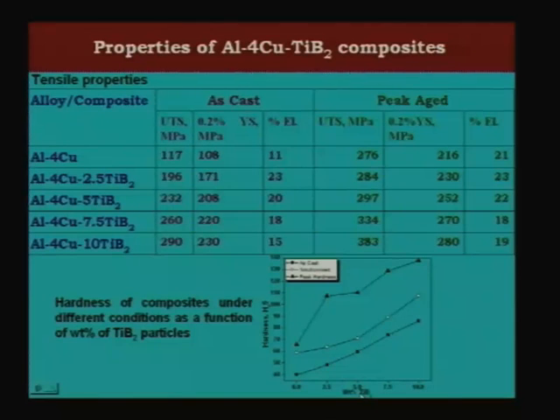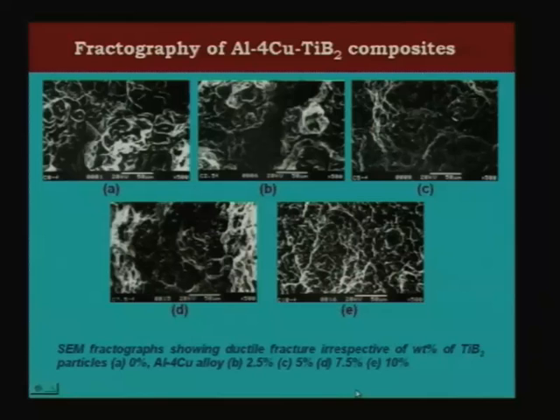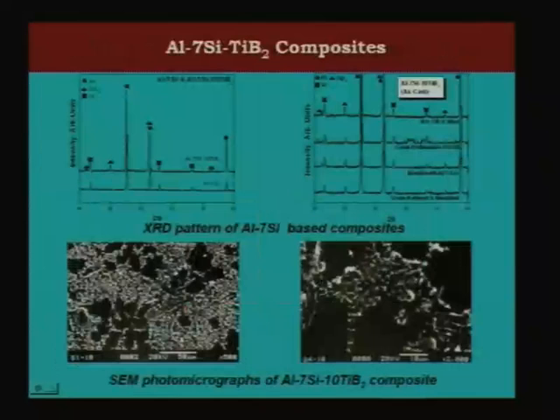Okay? And this is as far as the fractographs are concerned. You can see that even with 10% you have some dimpled fracture. This is what I wanted to say. And this is about silicon. If you take the silicon and you do the same thing with TiB2, you can see the fine uniform distribution of the TiB2 particles in the matrix with about 10% TiB2, and you can see that aluminum 7 silicon without any TiB2 will give you only aluminum plus silicon peaks, and the moment you add TiB2 you start getting the TiB2 peaks also.